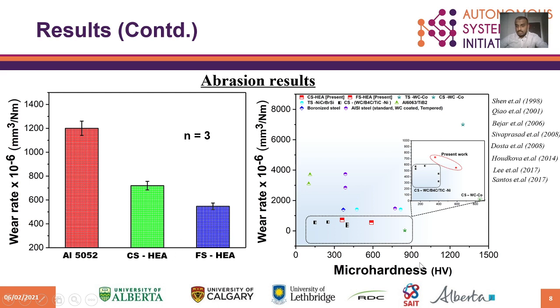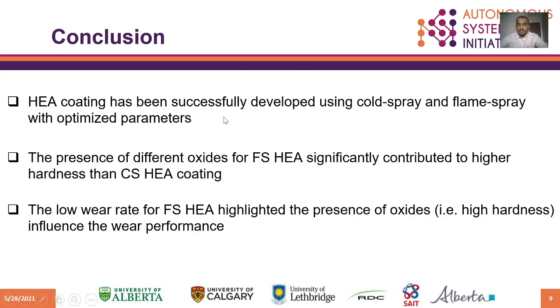The comparative study shows that both the coatings are 2 to 9 times better than the traditional materials and the thermal spray tungsten carbide cobalt coatings, and more or less similar to that of cold spray tungsten carbide coatings. In conclusion, HEA coatings have been successfully developed using cold spray and flame spray deposition techniques within optimized parameters. The flame spray exhibited the presence of oxides that contributed to higher hardness, thereby the lower wear rate for the flame spray HEA compared to the cold spray HEA coating.